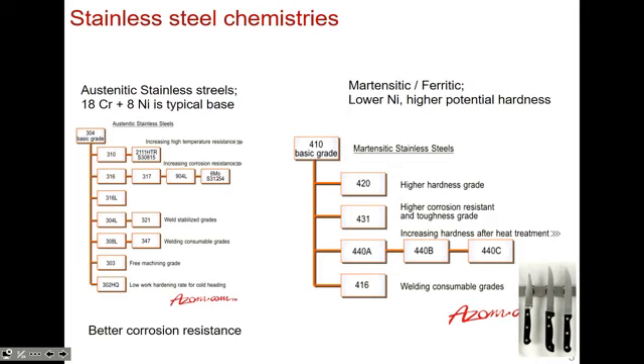Same thing for stainless steels, right? You could see that for these knives that are attached to some magnetic component on the wall, they have to have some magnetic iron in them. Otherwise, they wouldn't hold up the same way, right? If you remember your demo where Paul, your TA, had the iron piano wire resistively heated, at a certain point the magnet dropped, right? It passed the Curie temperature, the 770 degrees Celsius point. And then beyond 910, it would phase transform from BCC to FCC, right? So if your stainless steel knife is magnetic like this, then okay, there's got to be some BCC iron in there, if you know it's a steel. All these things, you can sort of tell.